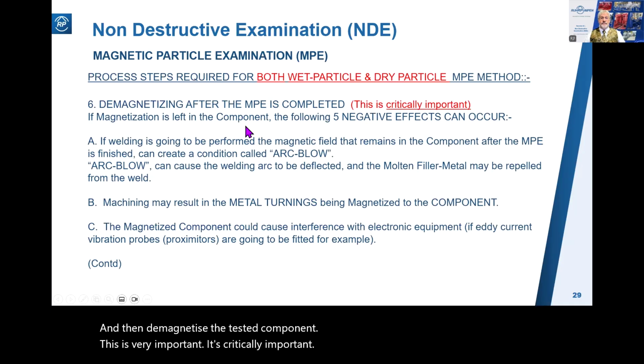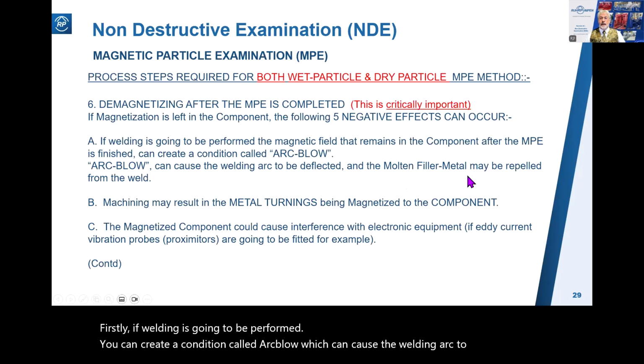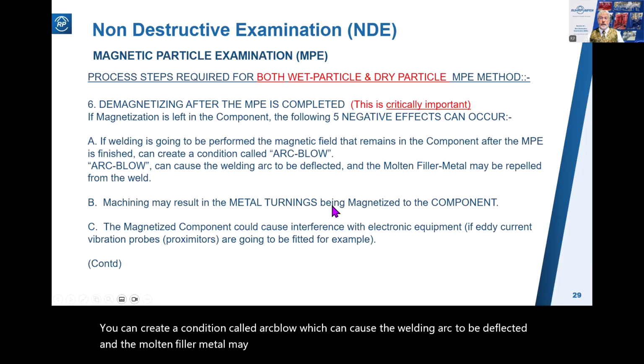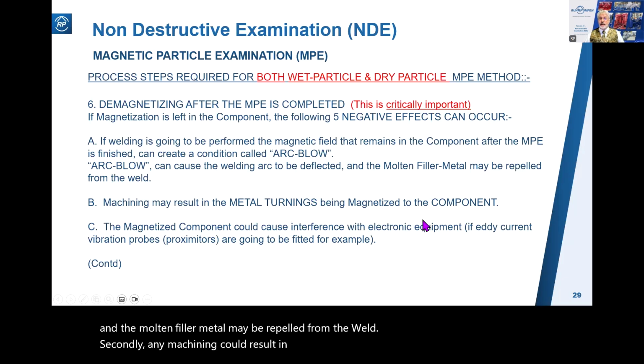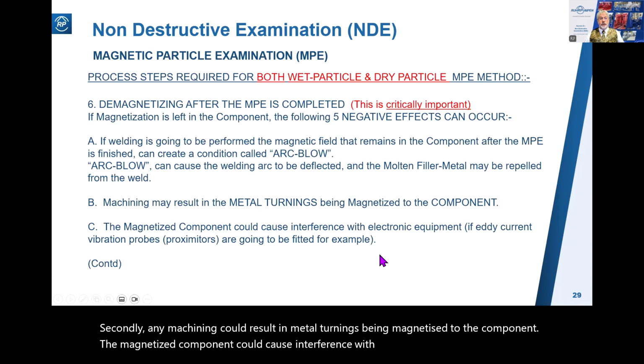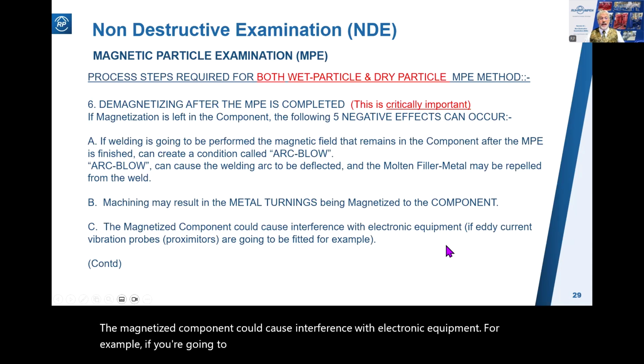If magnetization is left in the component, then firstly, if welding is going to be performed, you can create a condition called arc blow, which can cause the welding arc to be deflected and the molten filler metal may be repelled from the weld. Secondly, any machining could result in metal turnings being magnetized to the component. The magnetized component could cause interference with electronic equipment. For example, if you're going to use proximeters, eddy current vibration probes, they would be interfered with by the magnetic field.